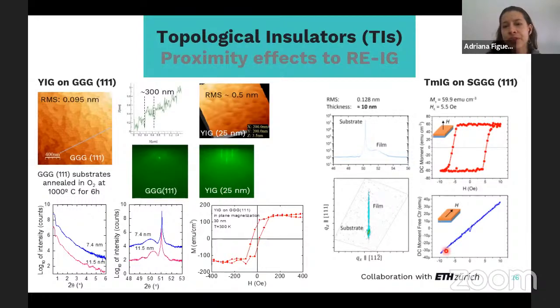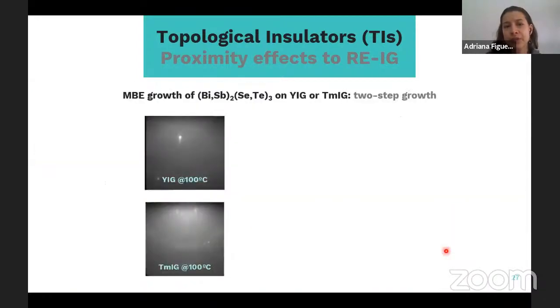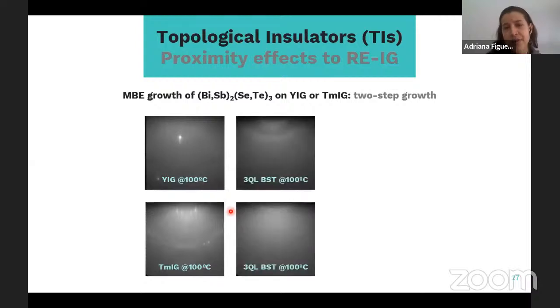And then we took these samples, these yttrium iron garnet layers, to grow the TI on top in the MBE. In this case, we performed the two-step growth, which means that we start with a low temperature growth. Then we evaporate what we call a seed layer of the TI on top.